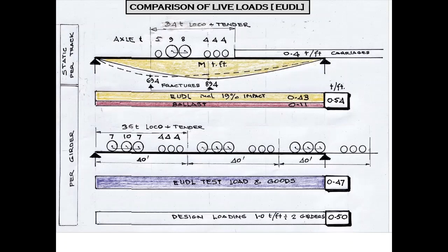I get 0.43 tonnes per foot equivalent load, whereas the bridge had been tested before it came into use, and for that test loading, they put 3 locomotives end to end on the train, each weighing about, I reckon, up to 36 tonnes, although we don't know the weights of them. I've assumed that 36 tonnes. You had 0.47, so it would appear that the loading due to the train which caused the collapse was less than test loading, which perhaps explains why the bridge hadn't collapsed before. But when you add the ballast, you add another 0.11 tonnes per foot, you get 0.54, which now exceeds the test loading and the freight trains that were using the bridge at slow speed. That all compares with the design loading of 0.5 tonnes per foot. So I think that explains why the ballast is a factor, and was one of the straws that broke the back of the bridge.